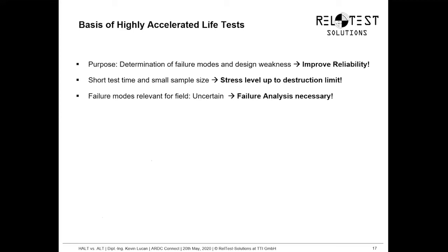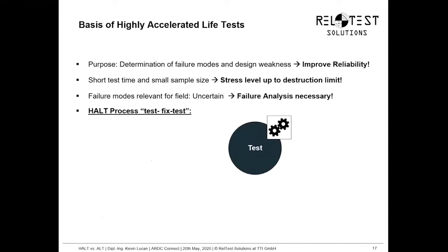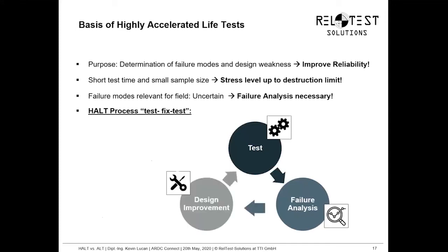Therefore, the highly accelerated life test can be described more as a test-based process. Starting with the test itself, then we are seeing some failures, and we have to analyze if the failures are relevant for the field load condition. After that, we can improve the design if it's relevant for the field load condition, and then we have to validate our design improvement. We repeat this process until we no longer see any relevant failures under field load in our product.